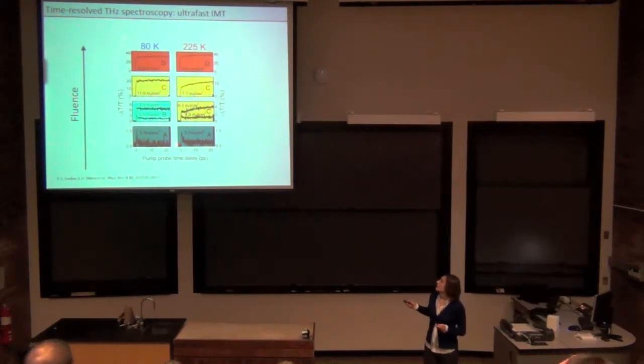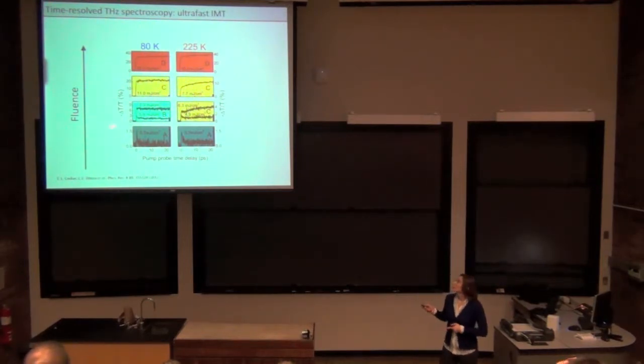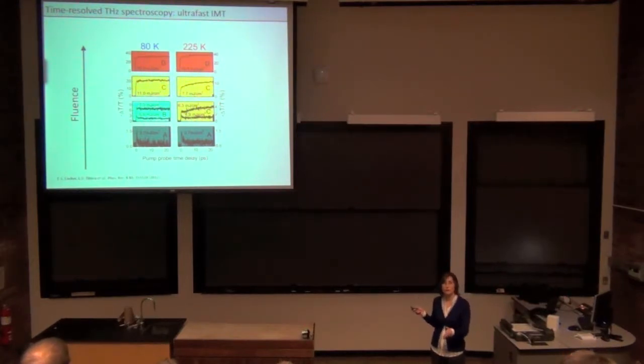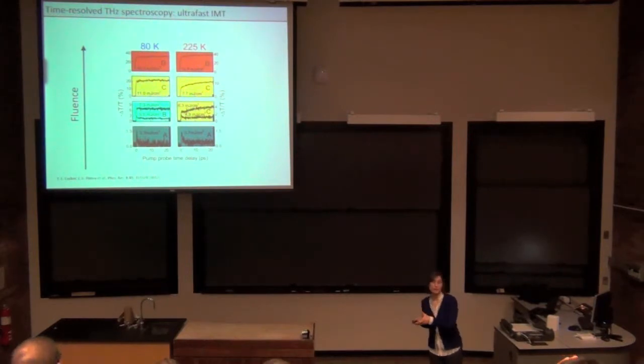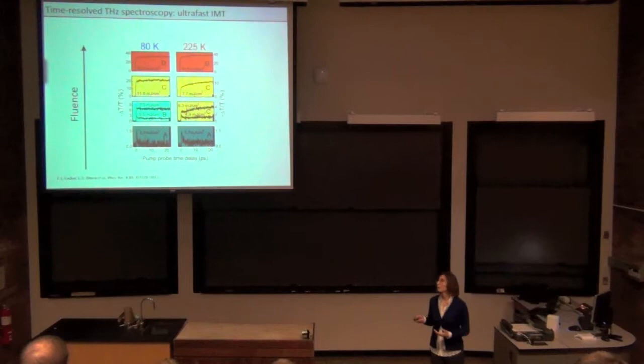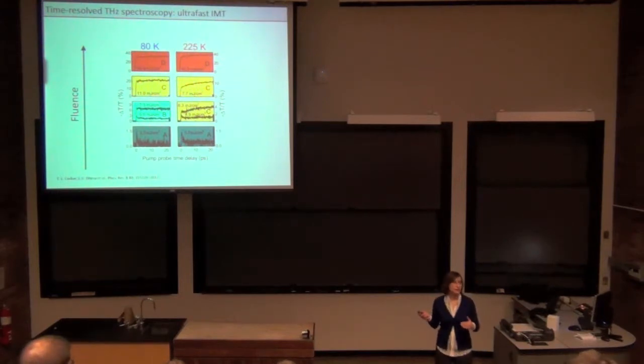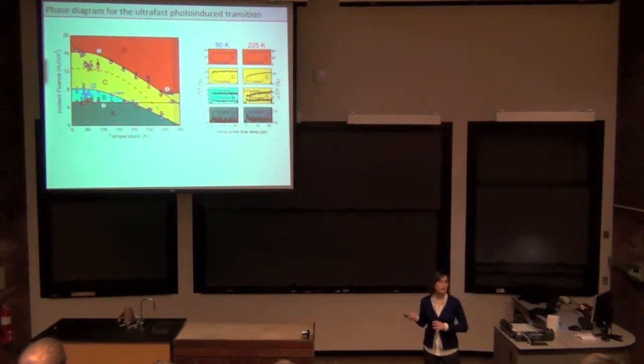The main thing is the induction of this metallic state, then also this slow rise transition, and the complete transition. To characterize the initial induction, we looked at the sensitivity at 5 picoseconds after photo-excitation. To quantify that slow rise, we look at the difference between the value at 25 and the value at 5 picoseconds. If that difference is considerably larger than 0, then we would indeed see the slow rise. And then finally, we've looked at the threshold for seeing the fully metallic state at either 5 picoseconds or 25 picoseconds. What we get is a phase diagram that looks something like that.